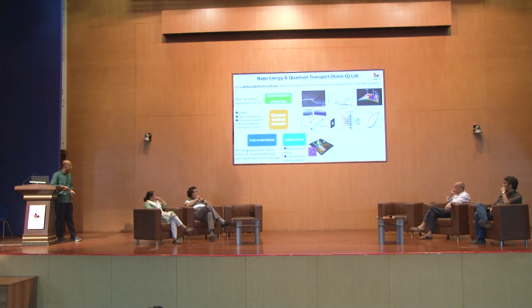And recently we also found that if you engineer these materials a little bit, this is not a completely monolayer, it basically started with a monolayer, but another layer is growing on top of it and there is a little bit of twist, so we call it a spiral geometry.